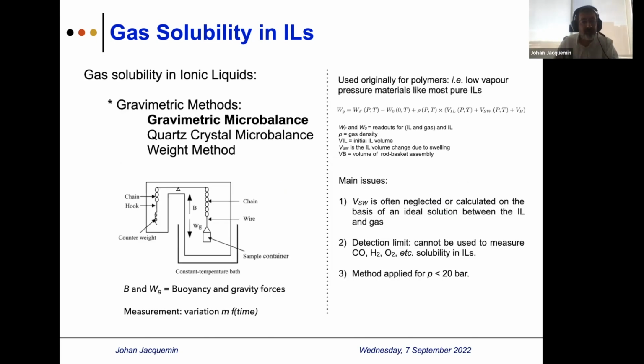And briefly, the gravimetric method. The gravimetric microbalance is based on gravity forces, buoyancy, of course, and within the equation, what you are measuring, what you need to do with this. Of course, you need the gas density. You need the molar volume, or the volume of ionic liquid, which means you need a density if you are just putting a well-known quantity of ionic liquid into your sample container. And you also need to know if this occurs, the swelling effect, the swelling volume, in order to take this into account in your gas solubility measurements.